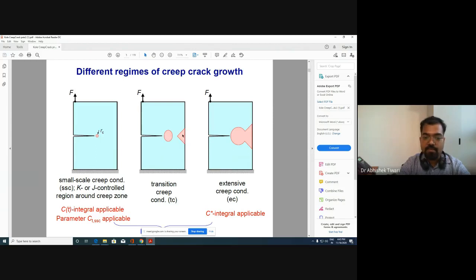So this kind of deformation will have stresses which you can differentiate, but strain you cannot differentiate. So stresses in the backside will be in compression and here the stresses will be in tension. So the creep zone has started growing both on the backside as well as on the crack tip. And after a sufficient amount of time, these two zones will join.